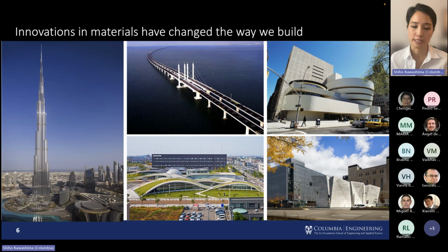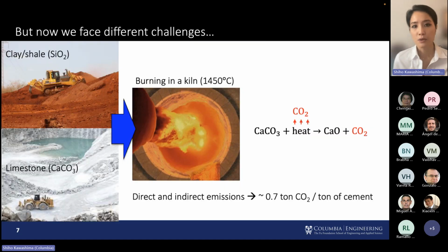So there's been a lot of innovations in material science, in cement-based materials, and that really has a direct impact on construction. And so we've been interested in high performance for a very long time. For a while it's really been focused on stronger and stronger concrete, which is important, and we've made significant progress there. But now we face different challenges, right? And I think we are all aware of this, but just in case, cement production emits significant CO2. And one of the reasons for this, or the key reason for this, is because we use a carbon-containing raw material. So limestone is one of the key feedstock materials for Portland cement production.